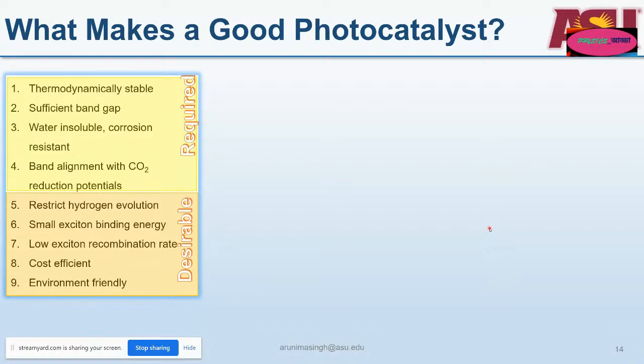So the first four include thermodynamic stability of the material. Your material should be stable. It should have a sufficient band gap so that it can absorb a good fraction of the solar spectrum. It should be corrosion resistant. So if you place it into water, it should not corrode away. And it should have band alignment with the reduction potentials of CO2.